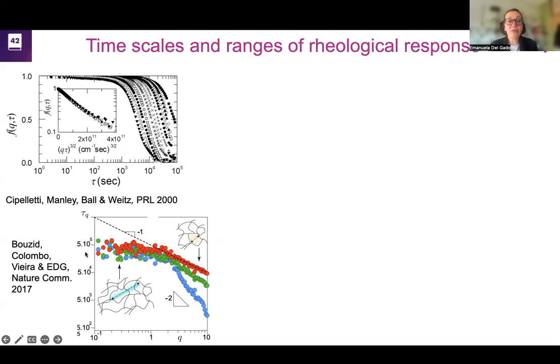And for example, a characteristic time is plotted here as a function of the wave vector. So now I'm measuring the characteristic time over regions of different sizes that are selected by the wave vector. And I can see that in this elastic regime, the relaxation time, in fact, grows as I decrease the wave vector. So it grows as I increase the size of the region that I'm looking at as 1/q, not 1/q squared, which is what I would think would be happening if the dynamics of these particles was purely diffusive. But in fact, it's 1 over q, so nearly quasi-ballistic, and really due to the elastic recoil of the gel network.